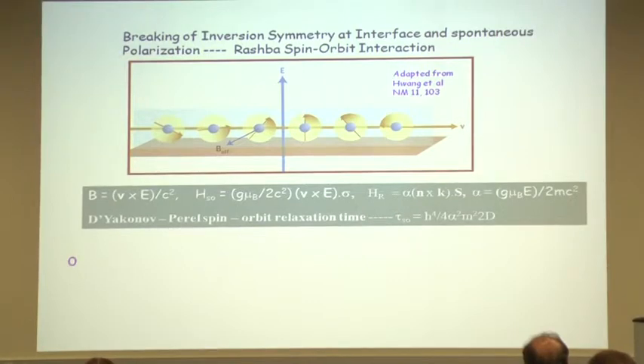And one more interesting example of this interface effect is the so-called, you have at the interface, you have breaking of the inversion symmetry. And once the inversion symmetry is broken, you have a built-in electric field at the interface perpendicular to the interface. And now if you consider one electron which is moving along the interface with a certain velocity v, in the frame of reference of this electron the electric field will appear as a magnetic field. And that magnetic field can interact with the spin of the electron and lead to spin precession. And this is the so-called Rashba spin orbit interaction.